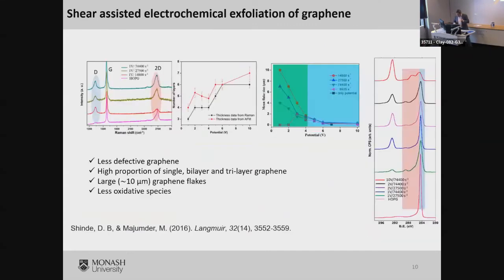So this was a reasonably old work in 2016. We were able to produce very large graphene flakes, less defective graphene, single, bilayer, trilayer graphene, where we imposed both shear forces and electrical potential. And also it has got much less oxidative species. So there are advantages of this approach.